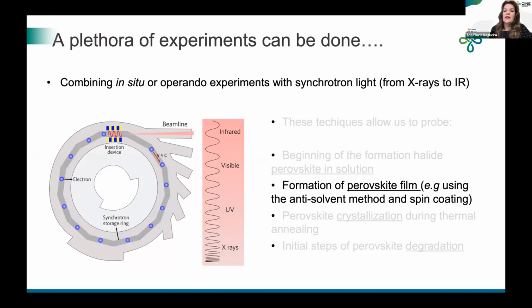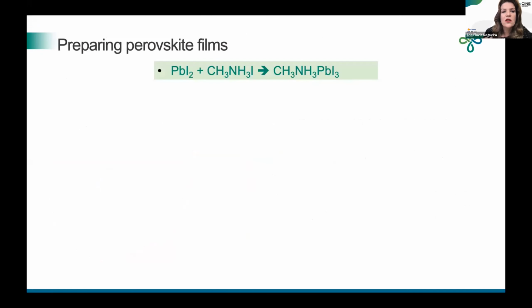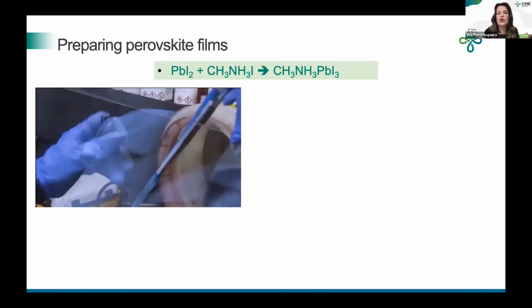But okay, let's now go to the 3D perovskite film that we use for solar cells. We can even compare, for instance, two different methods of preparation, the anti-solvent and the spin coating method. Preparing perovskite films is very easy. It's A plus B equals C. You just mix two precursor solutions, as I showed you before. But you can do it in two different ways.